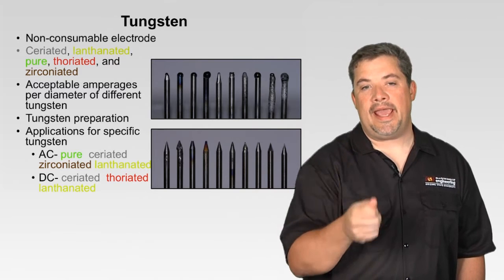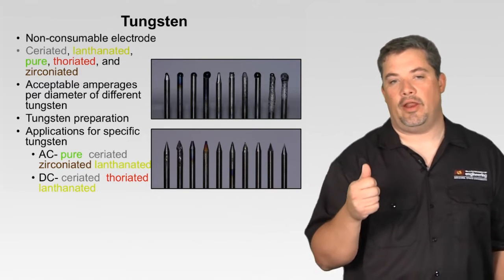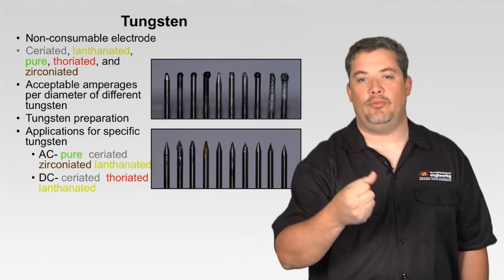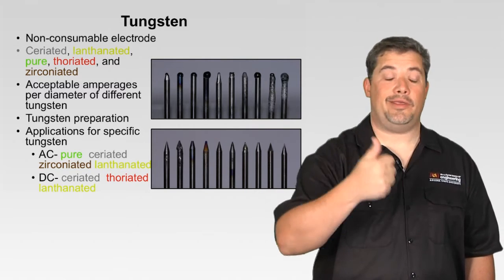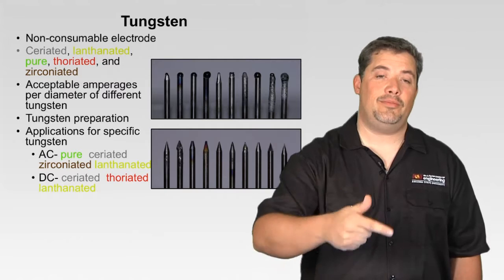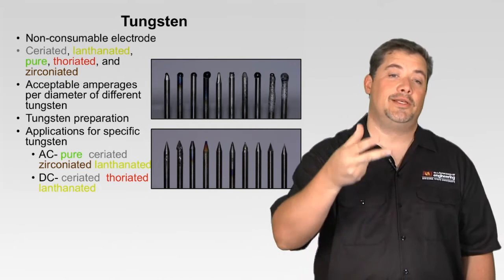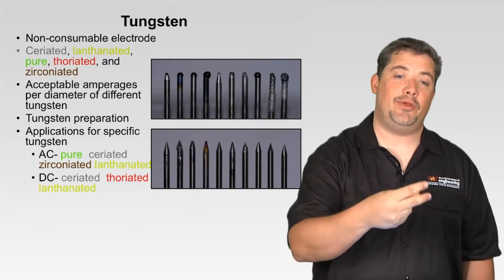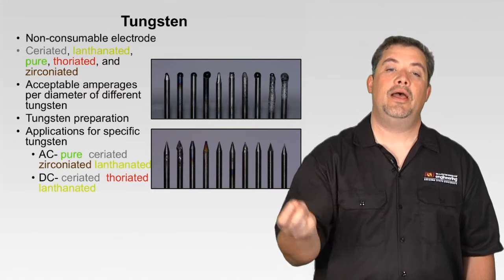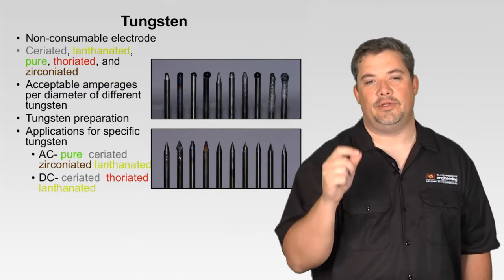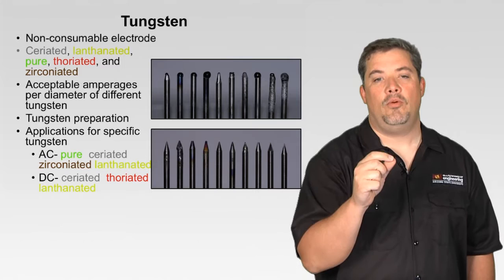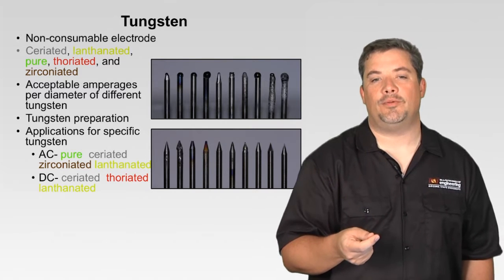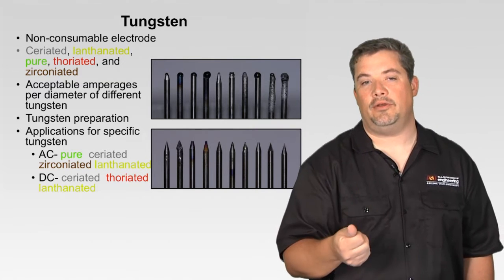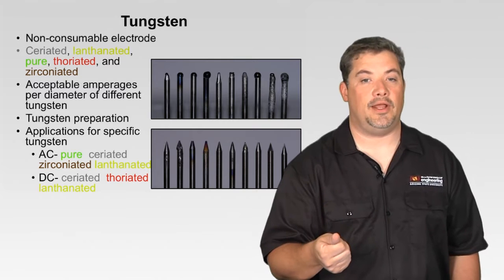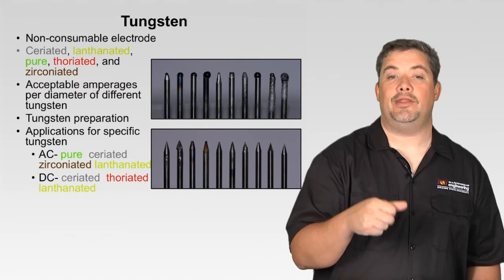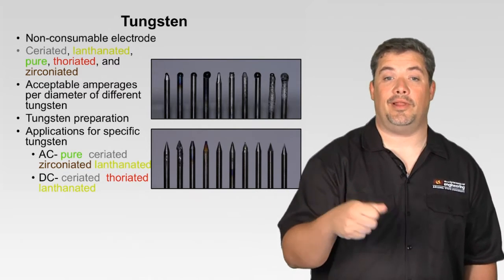So AC, alternating current, we use AC for aluminum. A for aluminum, I use AC. And what's like aluminum? Magnesium, very similar. So for aluminum and magnesium, we use AC to TIG weld them. All other metals, we typically use DC, direct current. So when we're on AC, there are a few tungstens we can use: a pure tungsten, a ceriated, a zirconiated, and a lanthanated. On DC, we can use a ceriated, a thoriated, or a lanthanated.